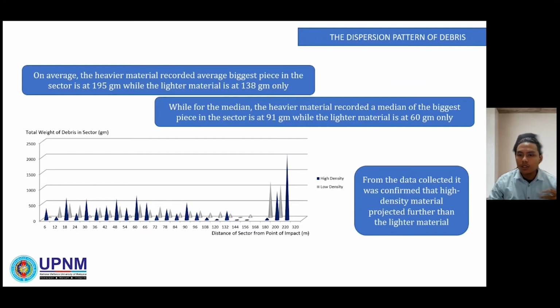From the data collected, it was confirmed that higher density material projected further than lighter material. Based on the figure shown, on average, the heavier material recorded the biggest piece in the sector at 195 grams, while the lighter material is at 138 grams only. For the median, the heavier material recorded the biggest piece in the sector at 91 grams, while the lighter material is at 60 grams only.